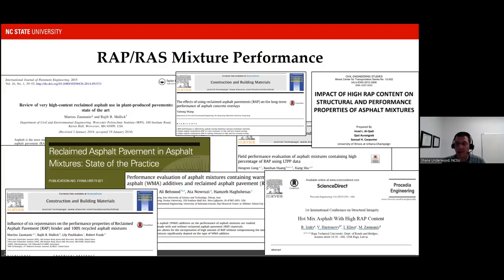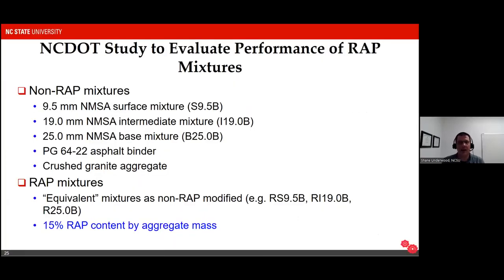affect the cracking performance. I want to talk about one small study that we did some years ago now for the state of North Carolina to investigate this. So what we did in our study was we obtained typical mixtures from the state of North Carolina. We obtained surface, base, and intermediate mixes. And then we obtained for those mixes so-called RAP equivalents.